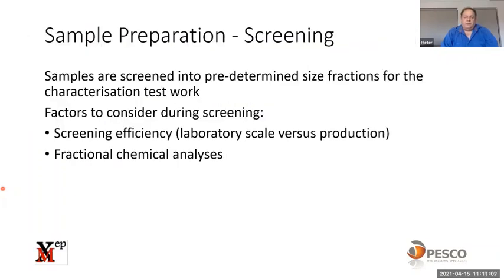Screening is the final step in your sample preparation. It's to screen the sample into the correct size ranges. It's also important when you do your screening in the lab, also take into account the screen efficiencies. There's a certain screen efficiency you can achieve in the lab, and there's a different screen efficiency you're going to achieve in the plant. So it's always important to keep that in mind. Also, the next information you can generate from your test sample before you start doing the characterization is to confirm the fraction analysis, to determine in what size fraction most of your valuable mineral will lie.